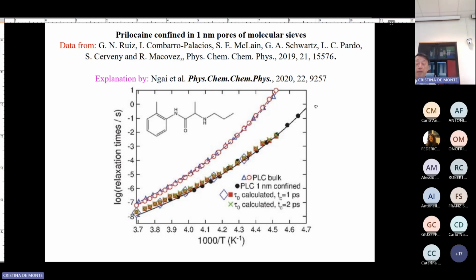relaxation time, I use the coupling model again. So the tau alpha is known, n is known because they already characterized the bulk. They know the shape, they fit it with the Kohlrausch function. So once you do that, I can do that immediately. It takes only about 10 minutes. And you calculate each data point with that. And you see lots of other points which are straddling the black circles here. So these are tau zero calculated from different measurements with the same material, and it's right there.